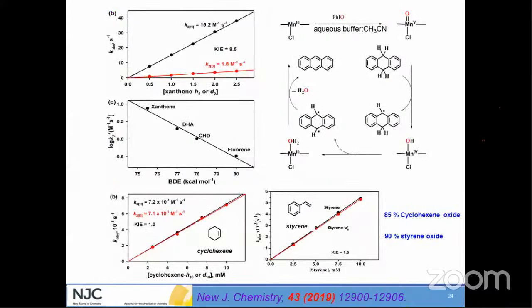When we did that, in the C-H activation reaction, we prepared the corresponding deuterated xanthene and reacted it with this manganese 5 oxo, and then we compared the KIE value. The KIE value was around 8.5. When you have 8.5, that is the first evidence which indicates the mechanism follows a radical mechanism, that is, hydrogen atom abstraction.